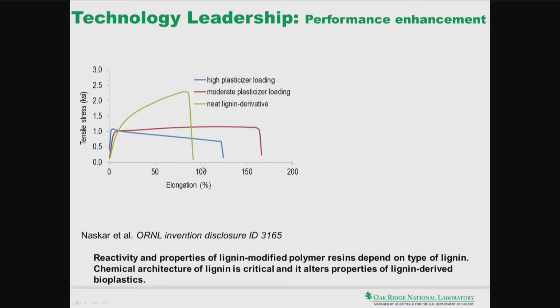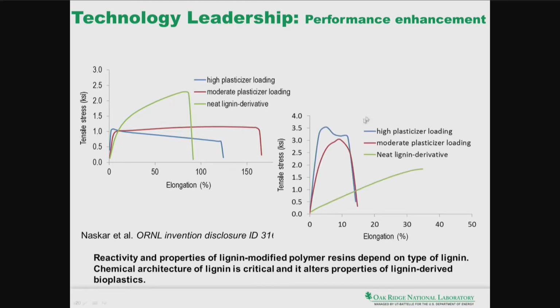Now let us look at the properties again in case of where it is showing the plasticizing effect, which is obvious. So neat lignin is shown in the green curve, and when we are adding moderate loading of plasticizer, then it dropped because of the softening effect. And then further addition, again it lowers the mechanical property, but it shows a little bit of yield stress, which is not that significant. Now when we did that for another group of lignin, as I talked earlier, you can see that it improved, and in fact it induces a great deal of yield stress and ductility in that material, although it is not that ductile, and we are currently working on it. It shows only 15% ultimate elongation. But the material is tougher than the previous weak lignin-based material.